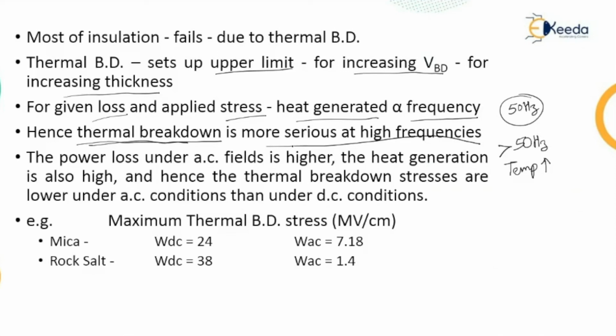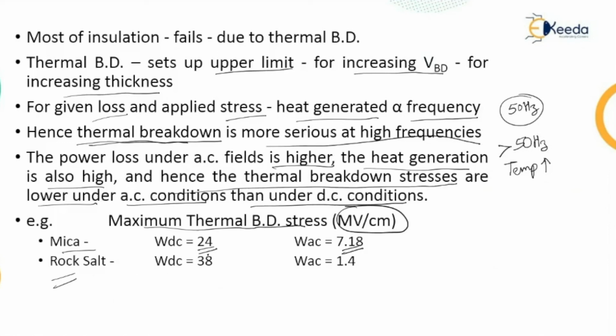The power loss under an AC field is higher, and the heat generation is also high. As the heat generation is high, the power loss is also high, but in case of AC it is higher. Hence, the thermal breakdown stresses are lower under AC conditions than under DC conditions. For example, the maximum thermal breakdown stress for mica is 24 megavolt per centimeter for DC and 7.1 for AC. For rock salt, it is 38 megavolt per centimeter for DC and 1.4 for AC.